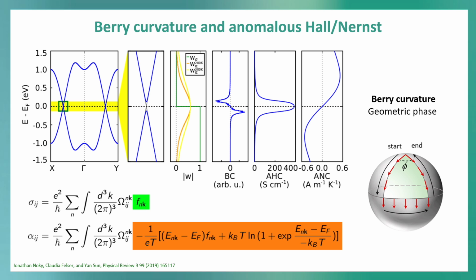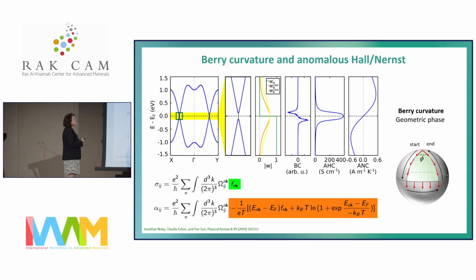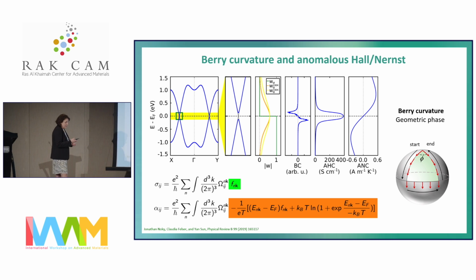So this leads to interesting properties. For example, the anomalous Hall effect in this material. This is an additional contribution to the Hall effect in magnetic material. It is very large in this material, and there is a large anomalous Nernst effect, and the Nernst effect is exactly what I want to have, a large Nernst effect for energy conversion, to take wasted heat into electricity.